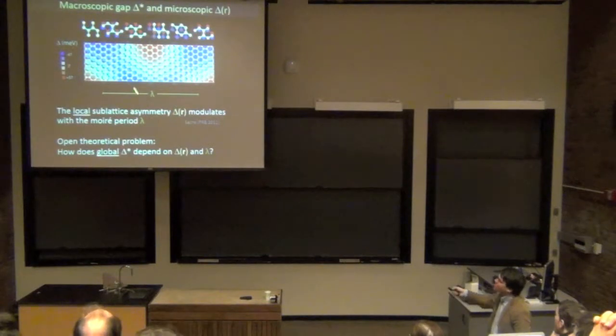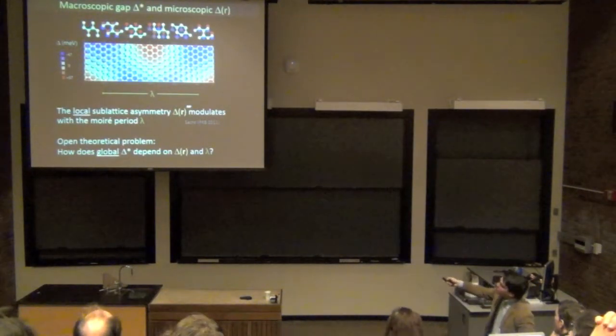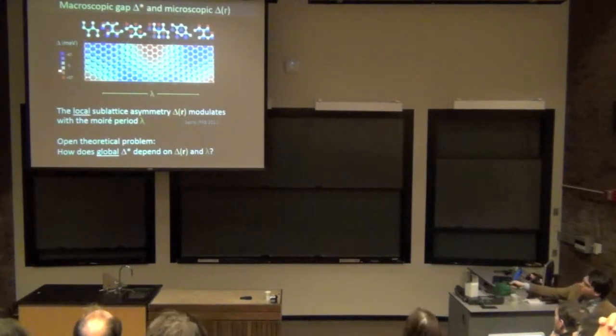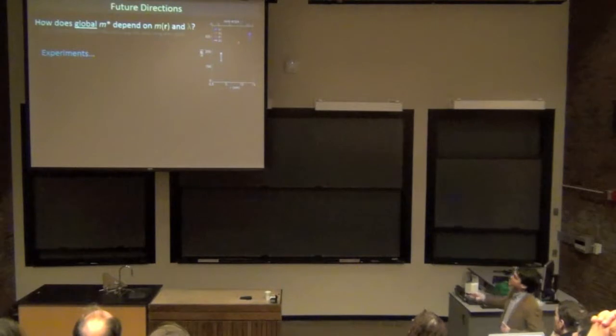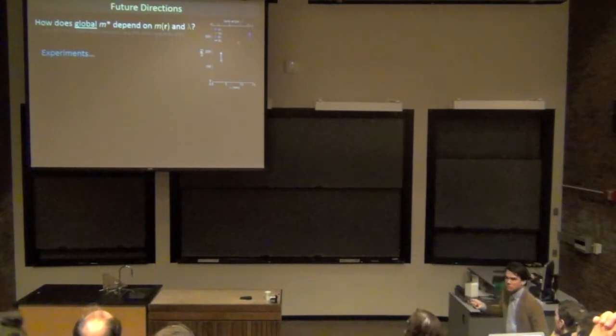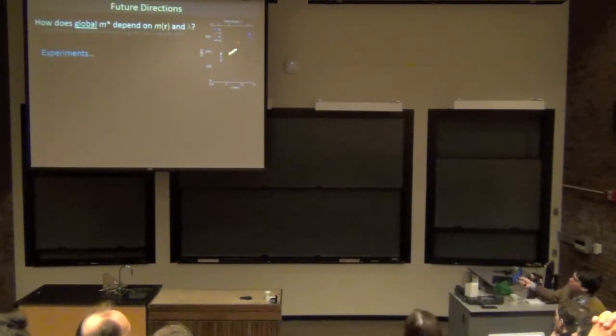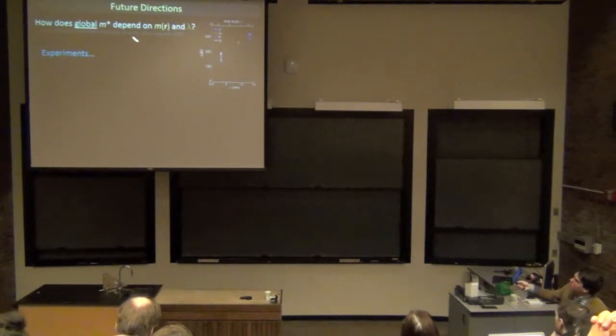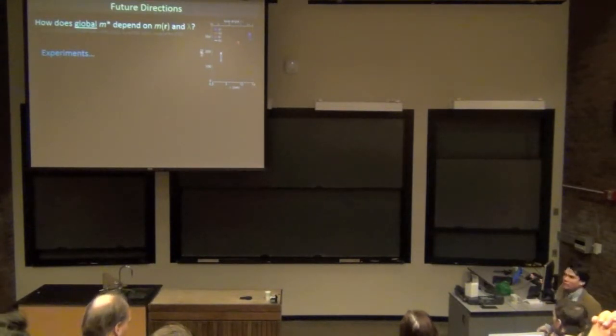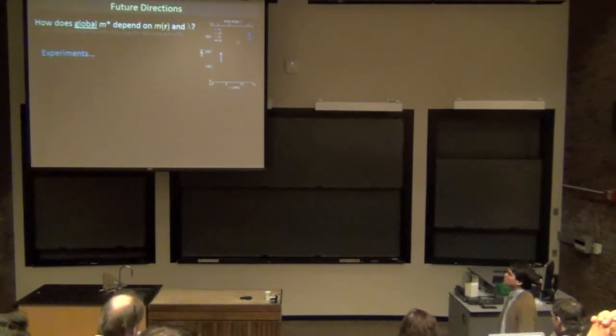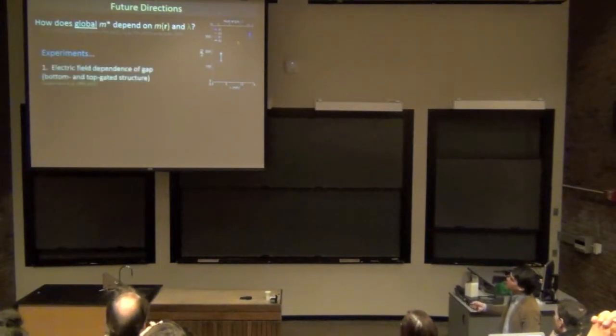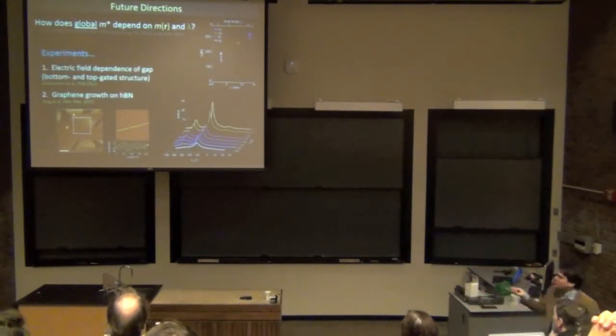And so this is an open theoretical problem. We see a gap, but we know that this periodic modulation of the gap should actually vanish. It goes from being positive to negative. And so that's basically where we are with this observation. Now we've observed this gap that depends on the twist angle, and we don't have a great theoretical description for where that comes from. So I'm gonna skip that part.